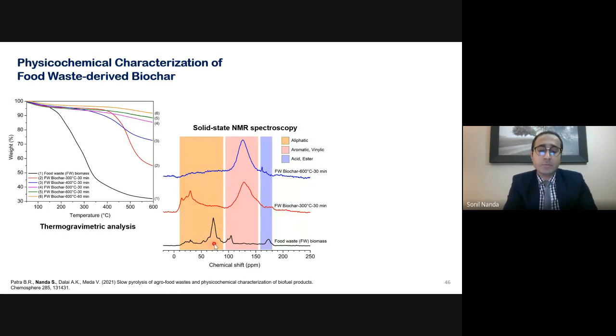Whereas there were some components which were initially present in the food waste like aliphatic groups, and gradually they lost their intensity and were completely absent in the case of biochar produced at 600 degrees Celsius, which indicates that these organic compounds, as a result of different deamination, decarboxylation, dehydrogenation, which means basically thermally cracking of the organic residues, produce different permanent gases and bio-oil. But in the biochar, what happens is the carbon-carbon bond strengthens, and these aromatic carbon moieties are enhanced when the biochar is produced at high temperature, indicating the promotion of the aromatization reactions.